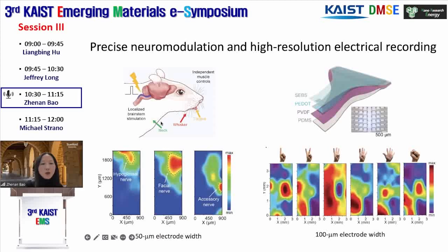And here we show the benefit of having small electrodes because of its low impedance for localized stimulation. That's represented here using 50 micron electrode size. We stimulate selectively various regions of the brainstem, which is the place where the spinal cord intersects with the brain, and it's an extremely sensitive region because there's constant neck movement, so having a rigid device here may cause severe damage to the soft tissue.